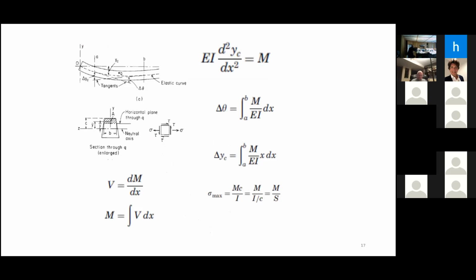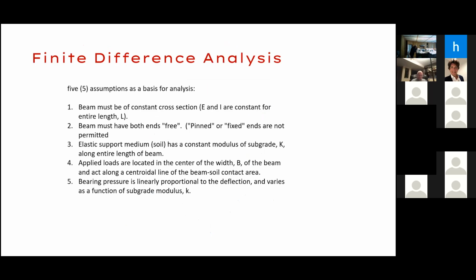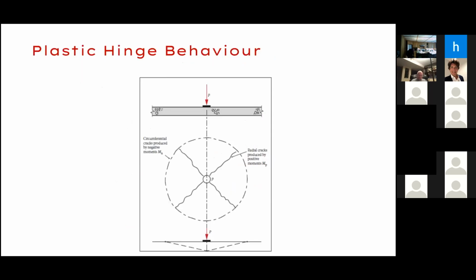And so instead, what we can do in our particular case is, with the presence of steel fibers, we can make a lot of assumptions about the performance of the slab that do not require us to worry about a single crack developing, as will happen in a brittle ceramic like concrete. If we instead consider what happens, we have a plastic hinge, much the same as we would if we were designing a piece of steel. And those of us that have been around for a little while remember when we did not use plasticity in steel. We used working stresses, and we kept below the yield strength. And we know that our ultimate limit state can be set to being some plastic deformation, and we increase the capacity and the performance of the same amount of material.